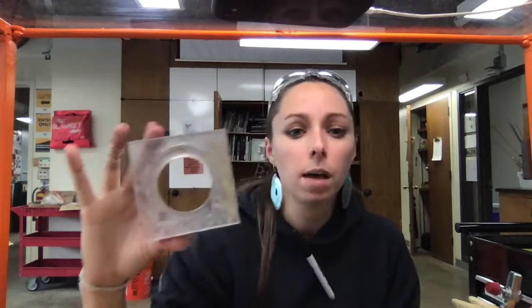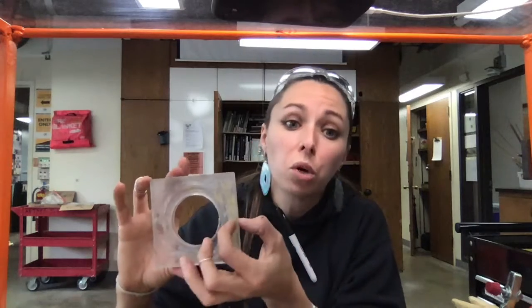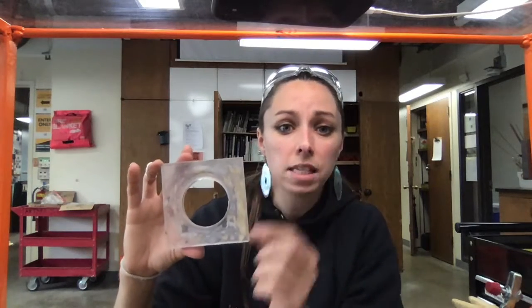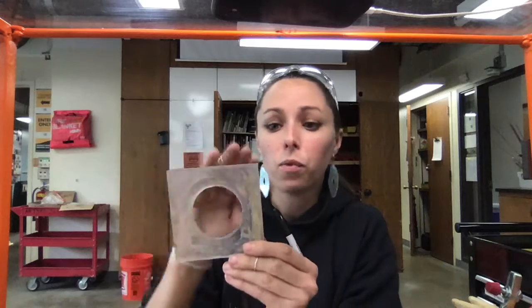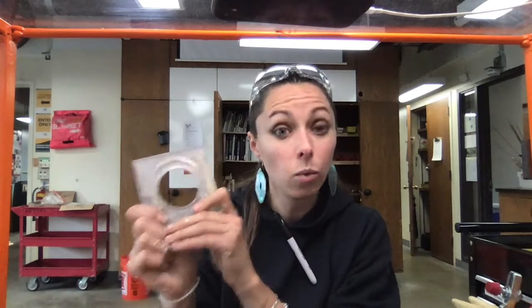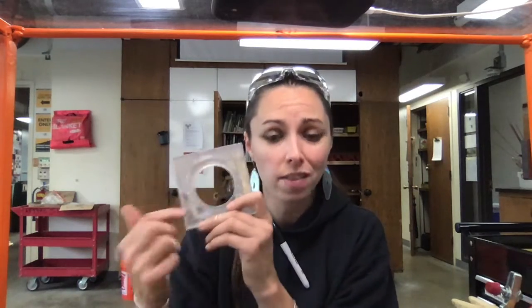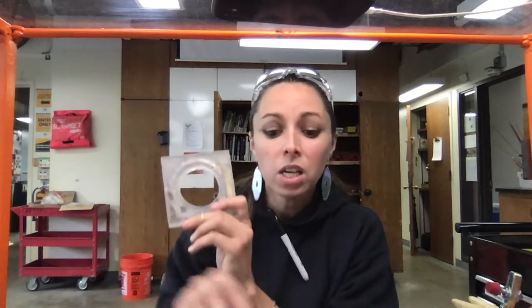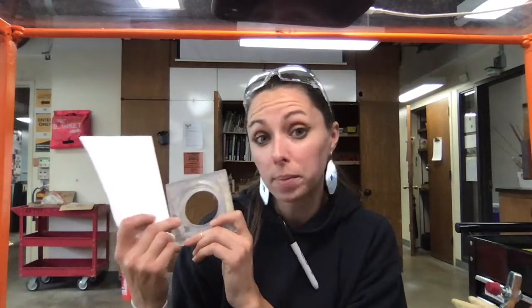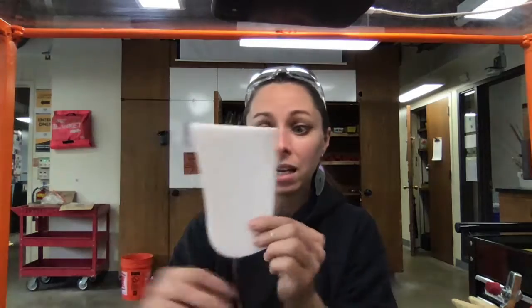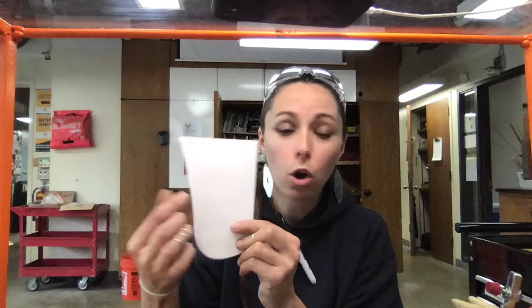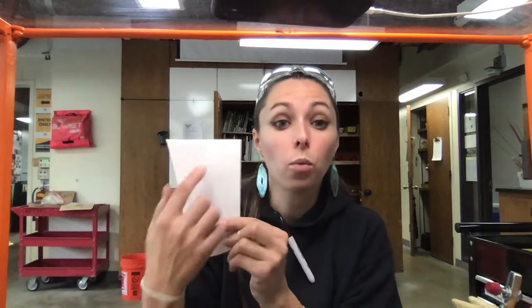And a good rule of thumb is anywhere between 3/4 and an inch on all sides of your die. It allows for the material of the die, the silhouette material, to retain its strength and not crack under all that pressure. So when you're picking out some of your scraps here, make sure that you're planning your die to be somewhere centered in the middle that allows you to have at least a 1/2 inch or at least 3/4 to an inch around your shape to support the die, to support the structure.